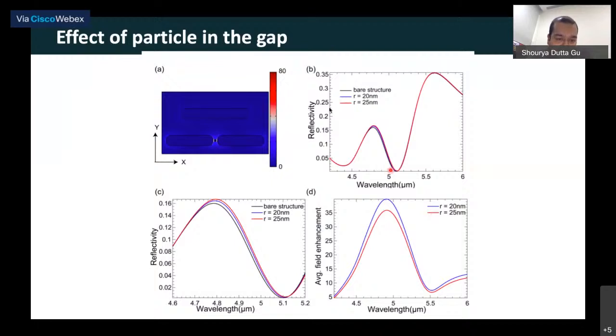So this is a simulation of that. So we are putting a 50 nanometer particle in this 100 nanometer gap and looking at the different changes in reflectivity we'll have, and the field that we'll have on the particle, right? So if I take the structure with and without particles, the response is shown here. So the horizontal axis is the wavelength and the vertical axis is the reflectivity. So if you notice, when I place the particles of two different sizes, 20 nanometers and 25 nanometers in radius, there'll be a small shift of the resonance. If I zoom into this region, I will see the shift much more clearly, right?